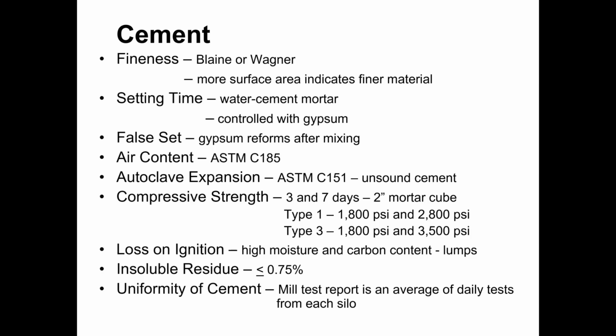This compressive strength is not indicative of what your compressive strength is going to be with your mix design. It's purely intended to be relative information so that you can make an assessment of how one particular sample is going to perform relative to another sample. So the compressive strength indicated on the mill report should not be extrapolated out to estimate a compressive strength for your mix design.